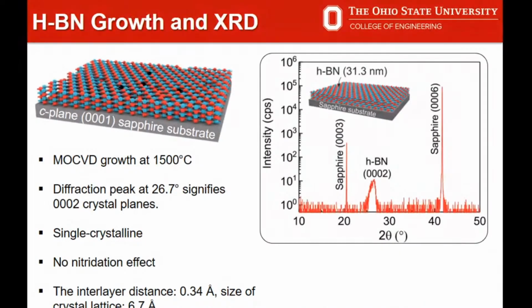So this is my work, whatever I have done so far in OSU. You could see this is the schematic diagram of my material, where I have grown this hBN on the sapphire substrate. The technology used by the Sandia National Lab is MOCVD, that is metal organic chemical vapor deposition, and the growth temperature was around 1500 degrees centigrade. And we have done the XRD.